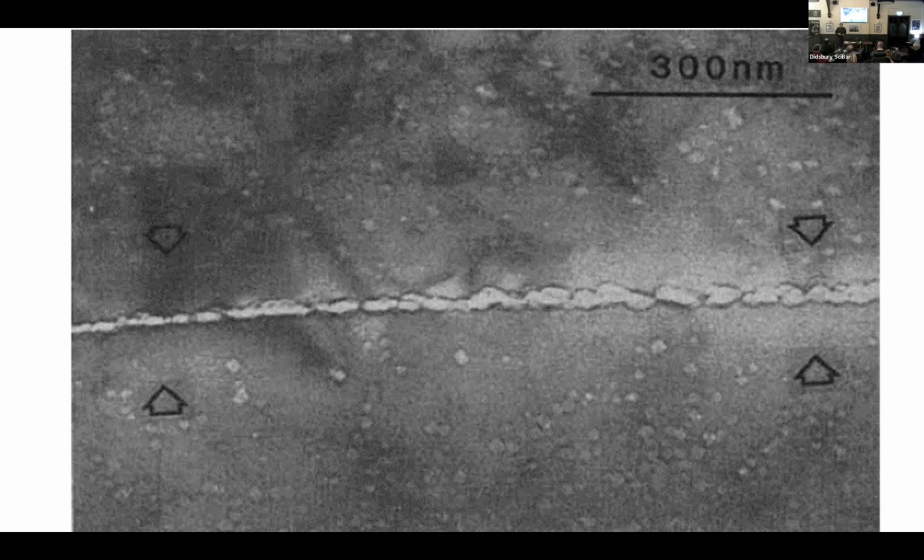So what we typically do is we use heavy ions, which is basically other atoms, and they generate similar damage, but not exactly the same. More importantly, they only generate a tiny, tiny region of material that we can actually study. When I say tiny, I mean a couple of microns. So this is a few human cells across. This is 1/10 the width of a human hair that we have to study.